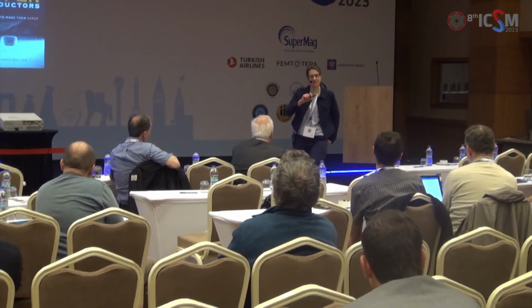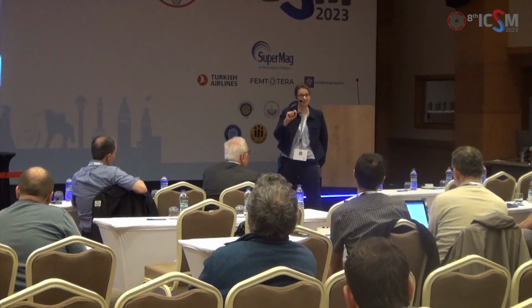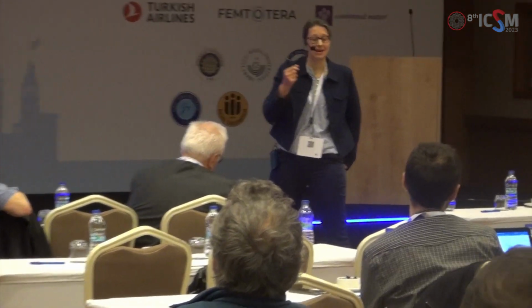What we're doing is we're sitting at one current and we're pulsing it, and we're looking for when we pick up some sort of voltage signal. So that isn't the same as saying we've measured IC. I didn't say that we find that IC drops by a factor of 3, but we're certainly getting instabilities in measuring at much lower currents. So it might be a similar effect to what you're seeing when you're getting the noise.